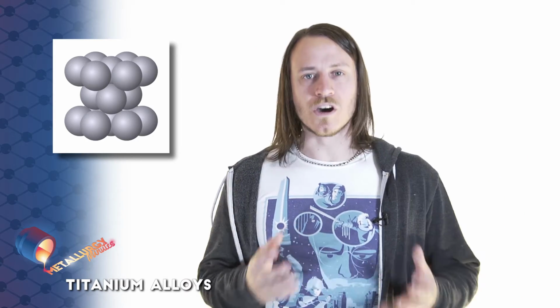Up to 883 degrees C, pure titanium has a hexagonal close-packed crystal structure. This is where the atoms form a hexagon with one more atom in the center, three lie on top of that, then the hexagon lies on top of that, and so on and so forth. Arranged in this manner, they have the highest density of atoms possible. This particular phase of titanium is called the alpha phase. If the temperature of titanium exceeds 883 degrees C, its crystal structure changes to a body-centered cubic arrangement. This crystal has 8 atoms at the corner and 1 in the center. It has a lower density than the hexagonal close-packed crystal structure. In titanium, this phase is called the beta phase.